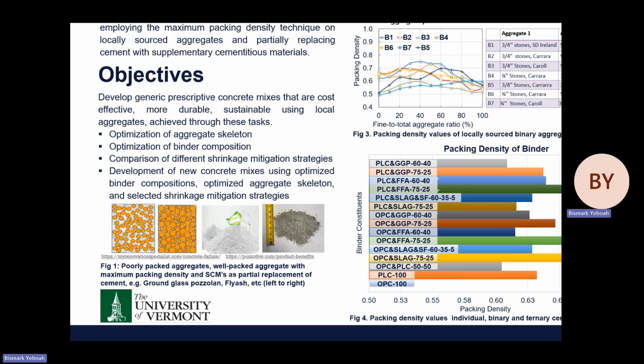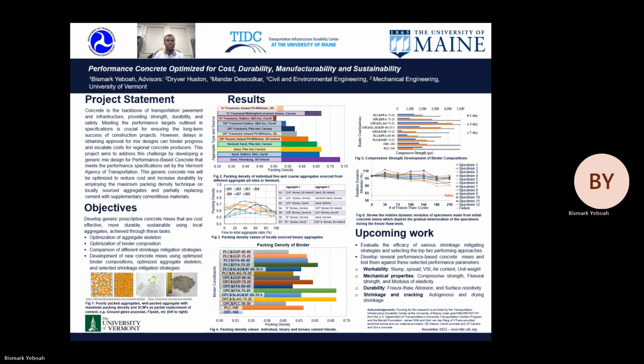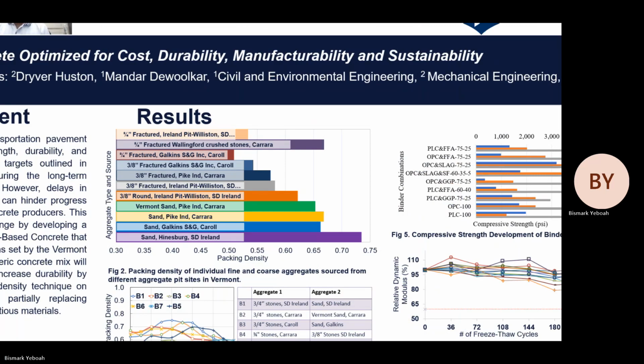So moving to results. Figure 2 shows the result of packing density tests of individual fine and coarse aggregates. The packing density test was done in accordance with ASTM C29, and from the results, the sand from SD Ireland had the highest packing density of close to 0.75, followed by Galkin sand from Carroll Concrete. Also, fractured stones from Wallingford by Carrara had the highest packing density of the coarse aggregates, followed by fractured stones from the Ireland pit by SD Ireland.